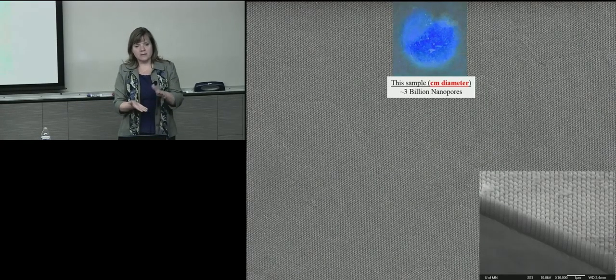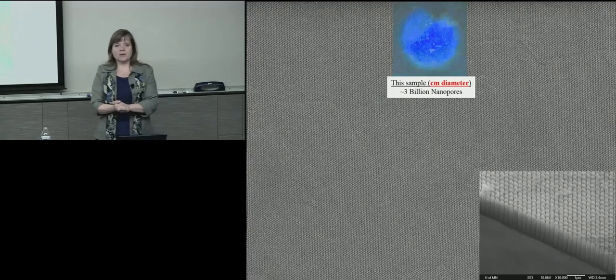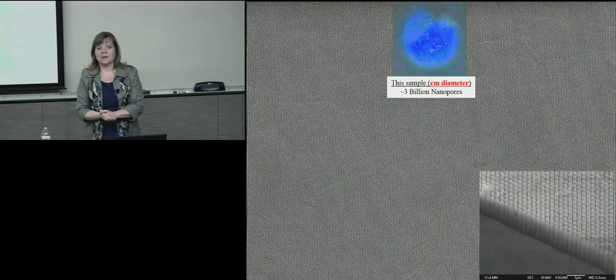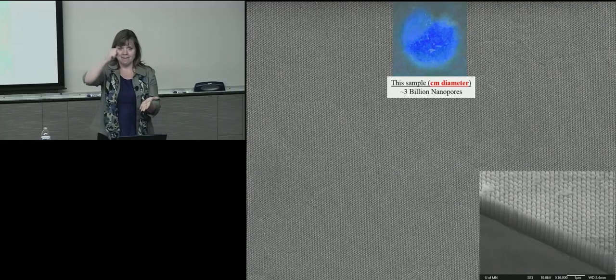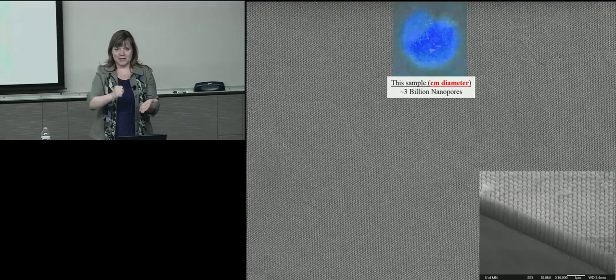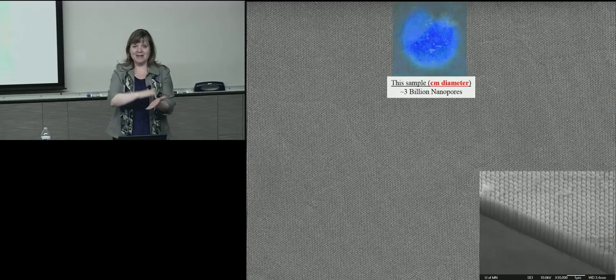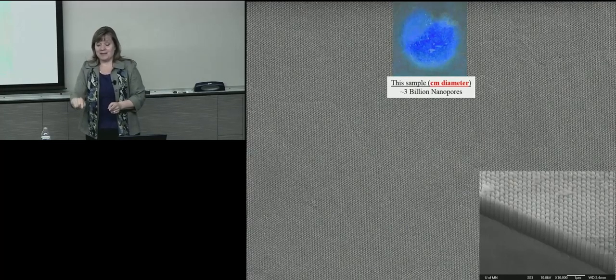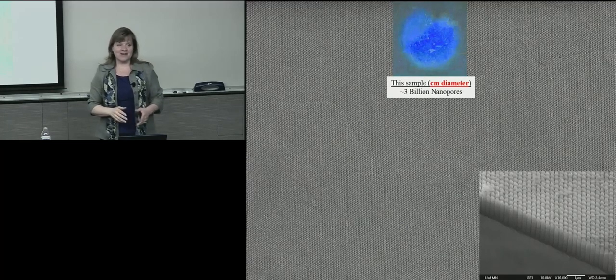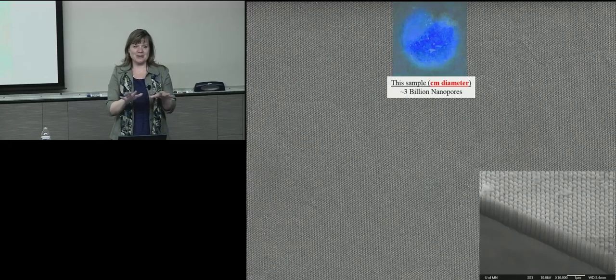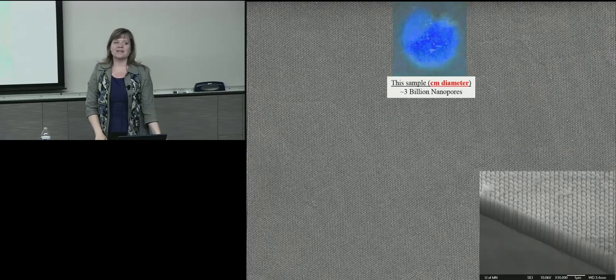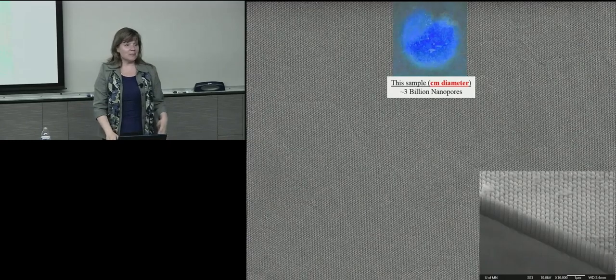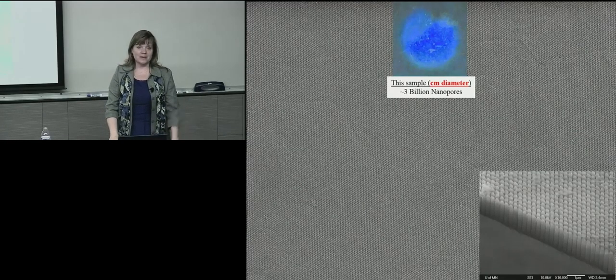And the imprinting, if you're very careful, let me just show you the motion we use when we nano imprint, and you might understand why we only get 20. It's a pneumatic, psh, psh, psh, right? And then we stamp, right? If we had sort of this as our motion, then we could get 100 stamps out of it because we'd have a controlled process. And you can see the automation that Seagate can do. So if they're at the point of being interested in it, they could go ahead and make a lot more imprints than we can make.